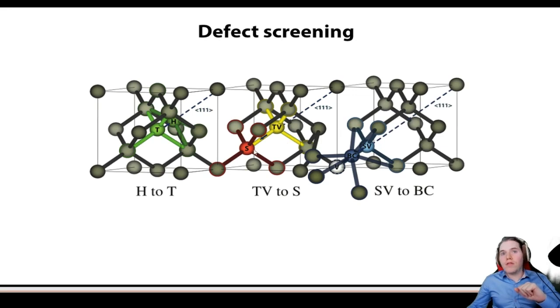Here we want to look at defects in silicon. These gray atoms here are what silicon looks like. This is the same as diamond. You can add other atoms in here which create defects, which are sometimes useful, for instance, to make a transistor like in your phone. Here we have three types of defect. One where you just push an atom in between the other atoms, one where you replace an atom, and one where you take two atoms out and then put another atom in, which is mainly interesting if you have a very big atom, else your crystal will get pushed apart.